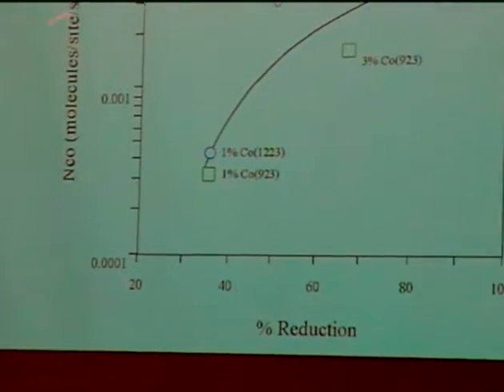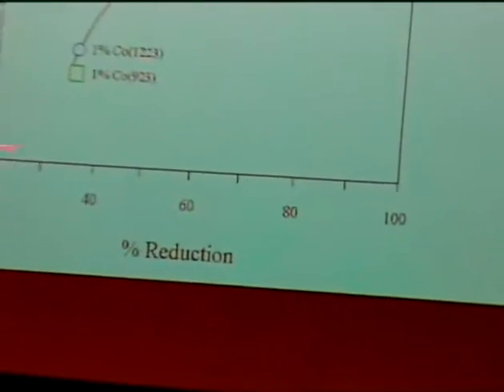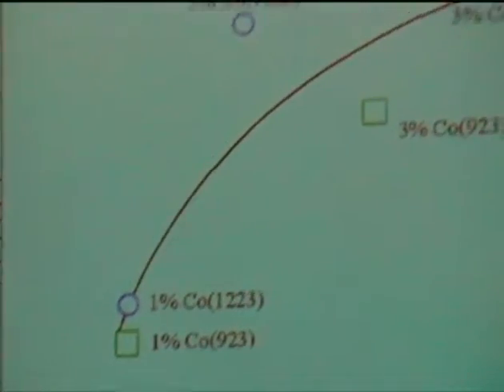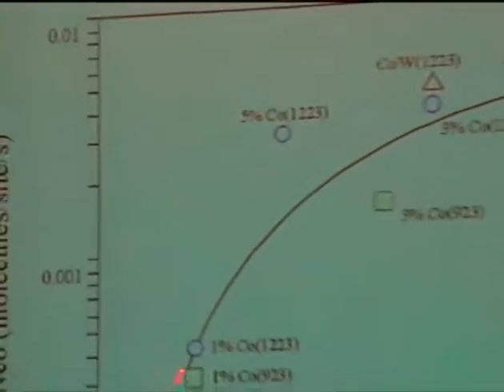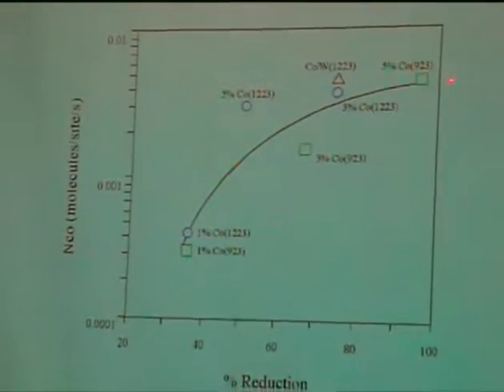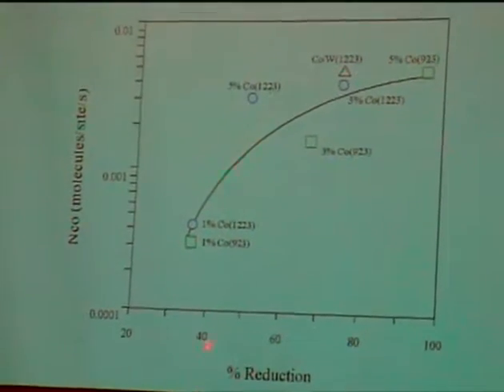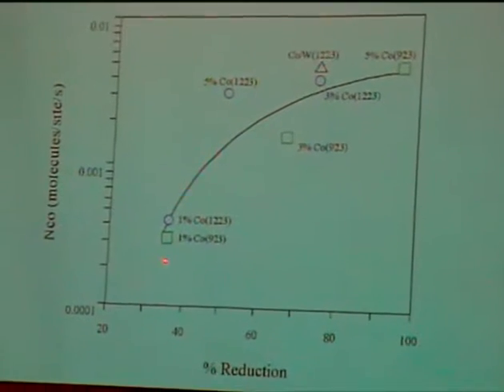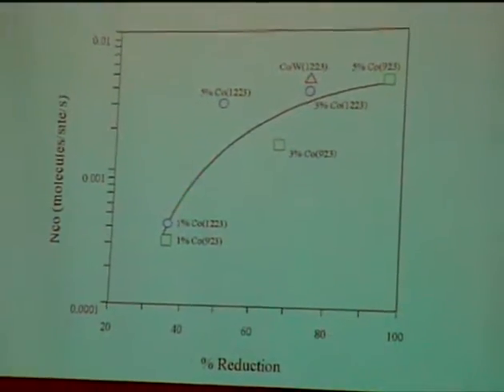In this work by Johnson and coworkers, we followed up on some of Rule's observations that activity appeared to correlate with extent of reduction. Indeed, we found that specific activity reaches a limiting value as you increase percent reduction from about 40 up to 90%.